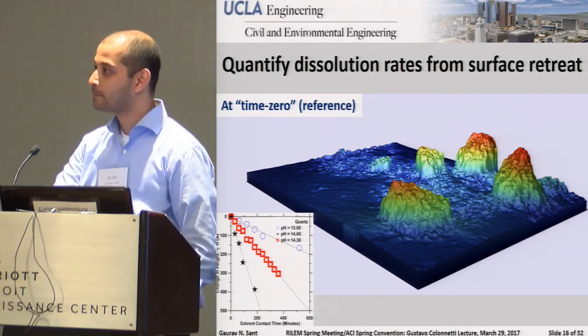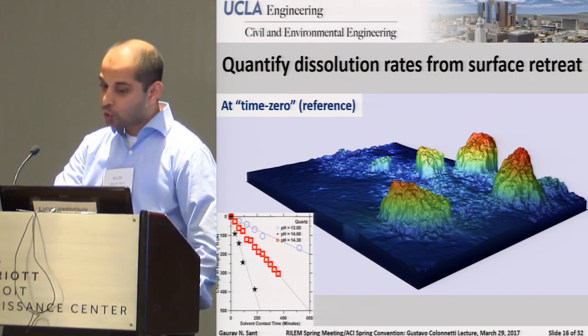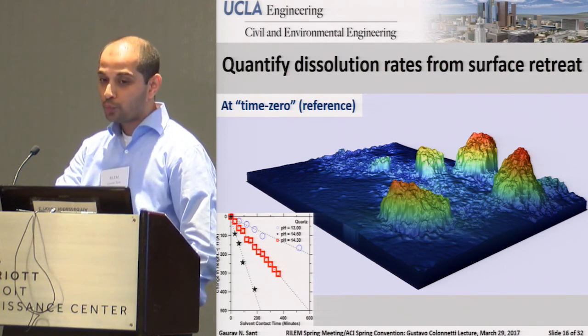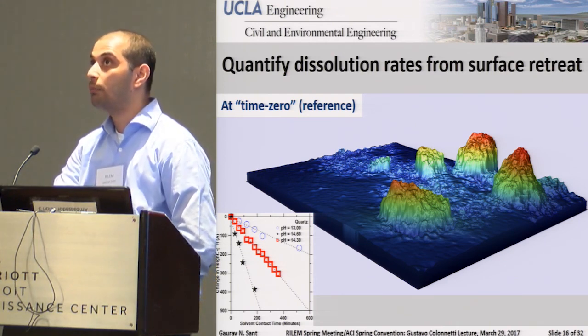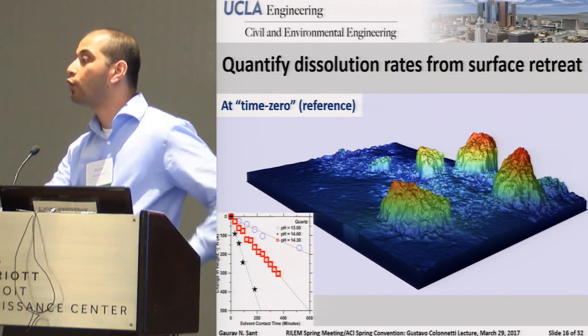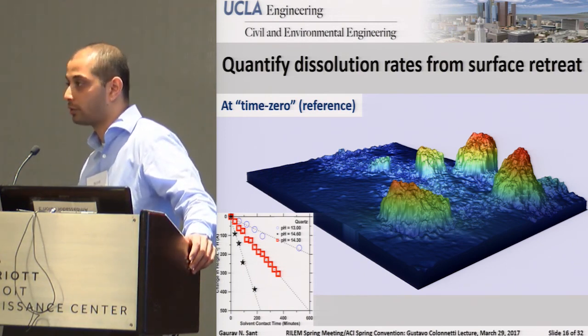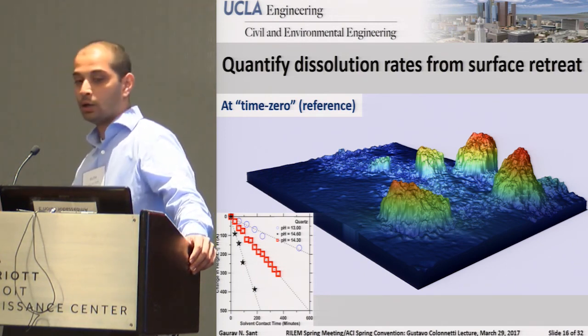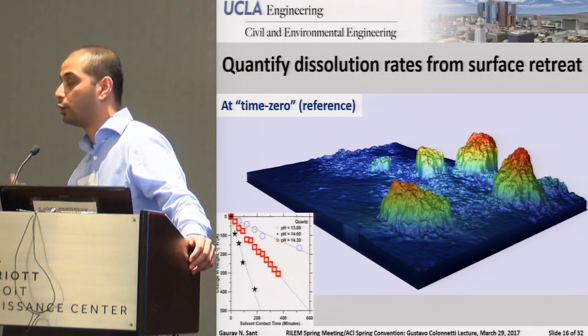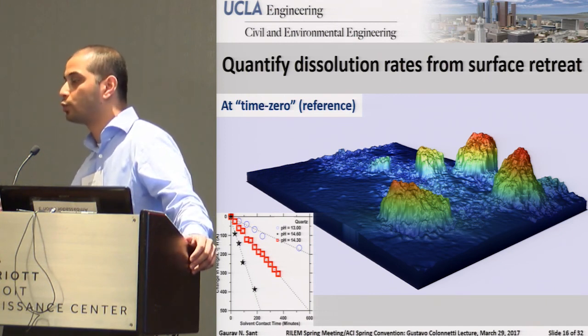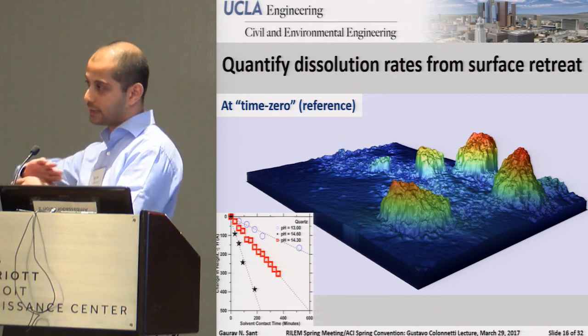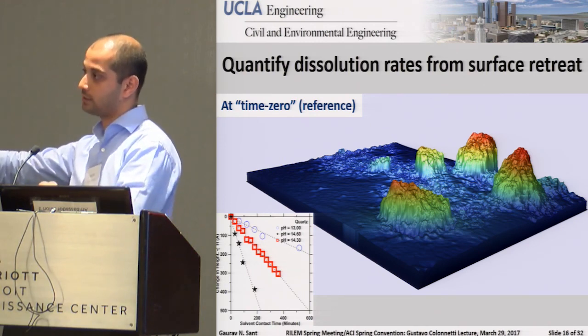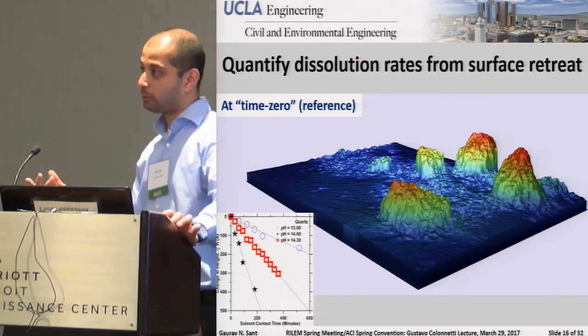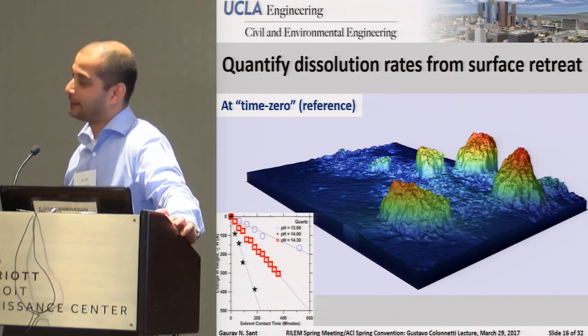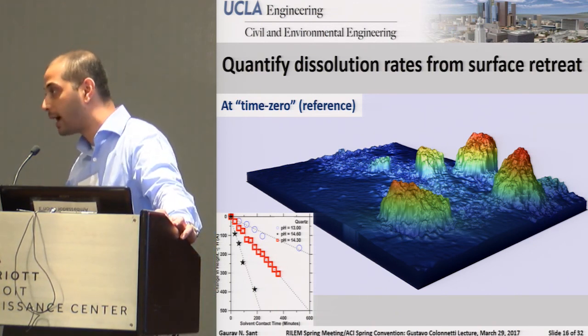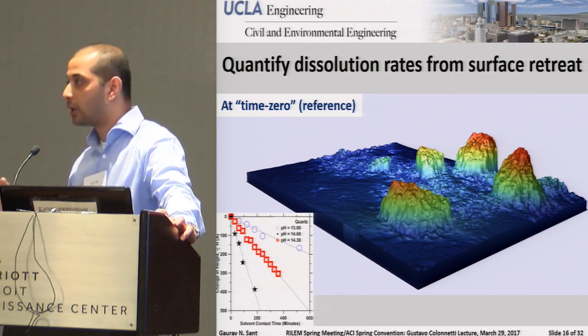And drying something? It's a good question. What I will tell you is that based upon our observations, we've not been able to see a dramatic change in topography. For example, we've tried taking a sample and drying it rapidly. The way we're doing it is essentially taking compressed air and blowing things off the surface of the sample. It causes a problem because, for example, if you have a loosely attached alteration layer, you might peel it back. But things of this sort you can identify.